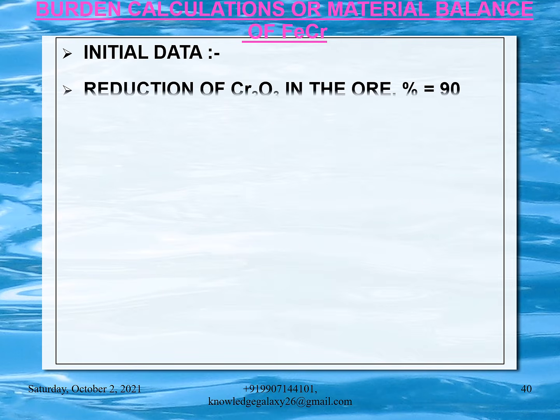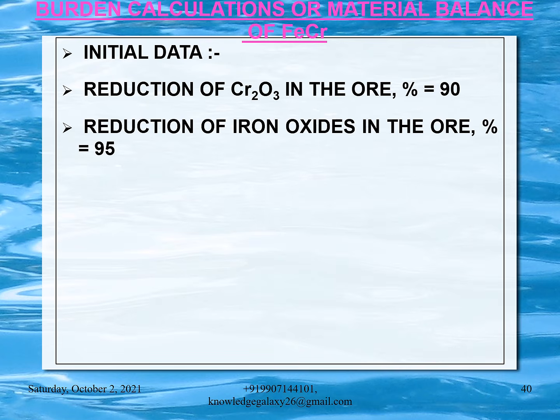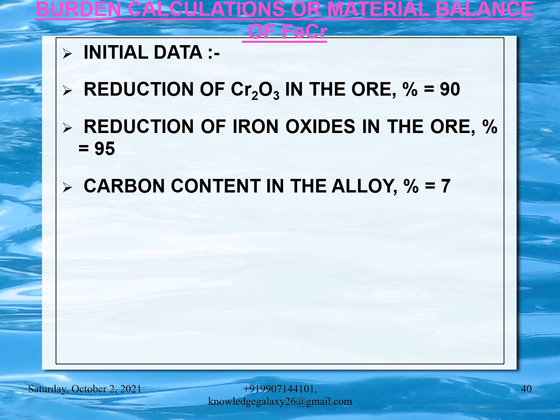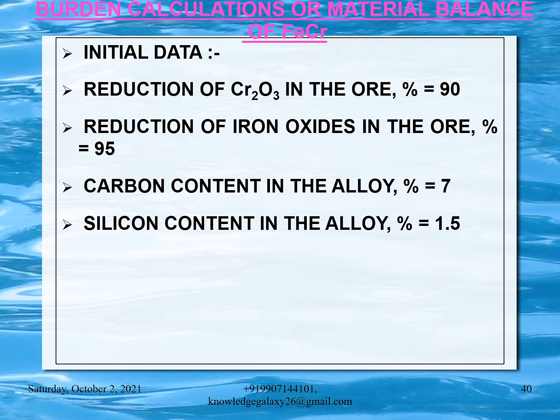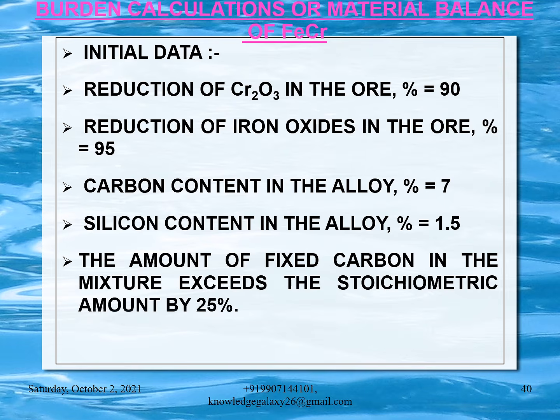Now, the most important part of the presentation is burden calculations or material balance of ferrochrome. For that, we require initial data, which can be taken as: reduction of Cr2O3 in the ore is approximately 90%. Reduction of iron oxides in the ore is approximately 95%. Carbon content in the alloy is 7%. Silicon content in the alloy is 1.5%. The amount of fixed carbon in the mixture exceeds the stoichiometric amount by 25%.